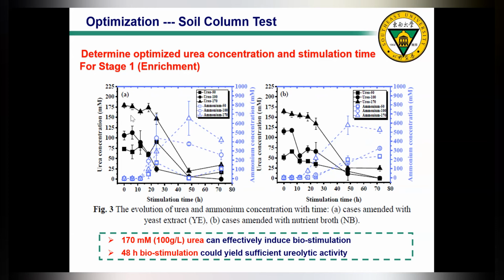Clearly, if we see the black lines and dots, we can see that with the increase in urea concentration, from 50 mM to 100 to 170 mM, the ability of the enriched bacteria to consume urea also becomes higher. It means that the generated ureolytic activity is higher. So from this test, we can see that actually 170 mM, or 100 grams per liter of urea, is sufficient to effectively induce biostimulation. That's already enough ureolytic bacteria enriched at this concentration.